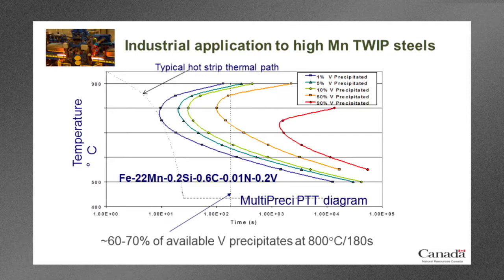First thing I want to point out is that in the hot strip, the blue curve here is the time and temperature at which 1% of all the vanadium has been precipitated. Going up to the red curve here, we have almost complete precipitation, 90%. This thermal path followed by the hot band after hot rolling and going into coiling just barely touches the 1% vanadium curve.